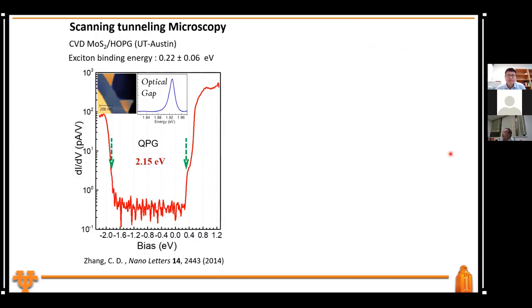Let's just go ahead and use the STM, right? Because with STM, you either extract an electron out from the valence band, or you add an electron in, and you measure precisely the quasi-particle band gap. Okay, so we did this in 2014, and we measured the quasi-particle band gap of MoS2, and we found it's about 2.15 eV.